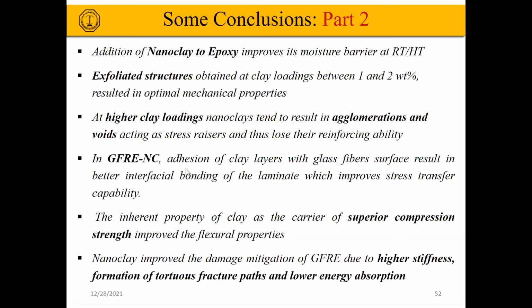Glass fiber reinforced epoxy with nanoclay has more adhesion to the fibers and increases the stress transfer capability. Superior compression strength of clay improved the flexural properties, and also the damage was mitigated by the presence of the clays, because they create a formation of tortuous fracture paths, and they result in lower energy absorption under low velocity impact.